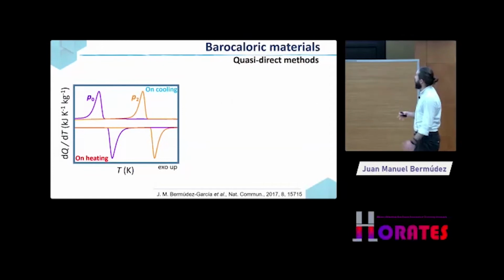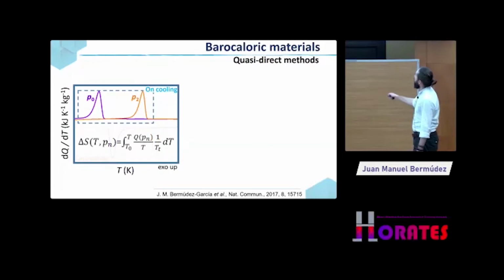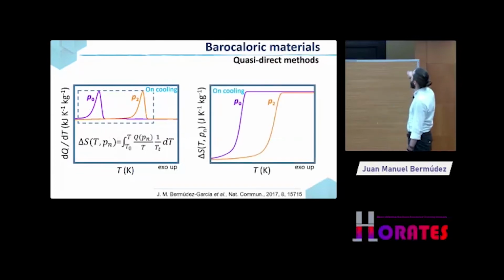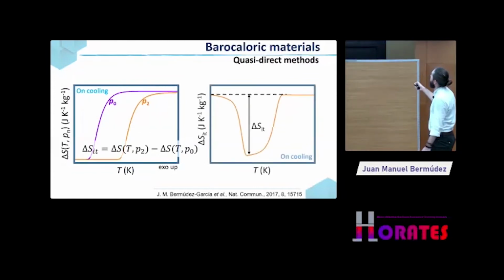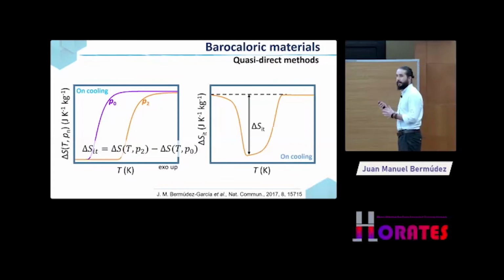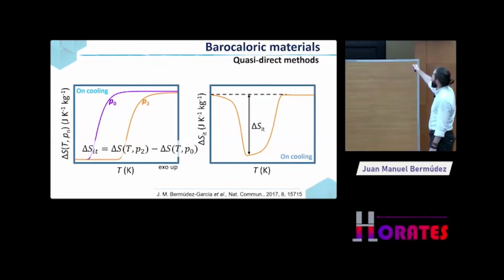So, with an example, let's do that first for the cooling ramps. Remember that was on heating and cooling. So, if we do that integration for both peaks on the cooling ramps, we have something like that, okay? Then we do the subtraction, and this subtraction is gonna give some curve similar to that one, and that is the curve which is called the isothermal entropy change of barocaloric effect. And as you can see, as you shift in temperature, this barocaloric effect is gonna be slightly different, okay? And that could be the maximum.